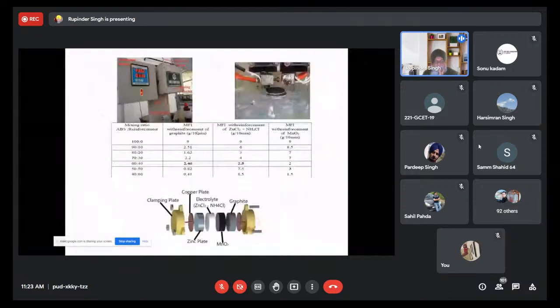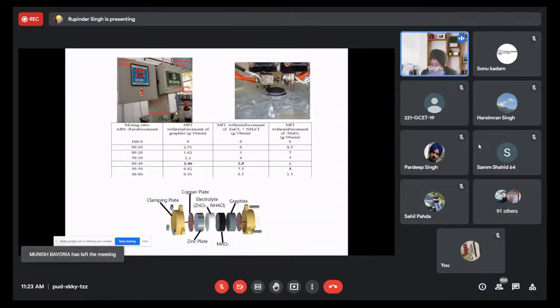So what we did in this case was we used different quantities of the reinforcement like the graphite powder, then zinc chloride and ammonium chloride, and then the MnO2. These different combinations were put to a tester called MFI. This is basically a melt flow index tester, which is giving us the value in gram per 10 minutes. You can take it as a reciprocal of the viscosity. In other terms, if I am having a high MFI, I can prepare the thin section. If I am having a low MFI, the preparation of the component for the thin section is really a challenge.